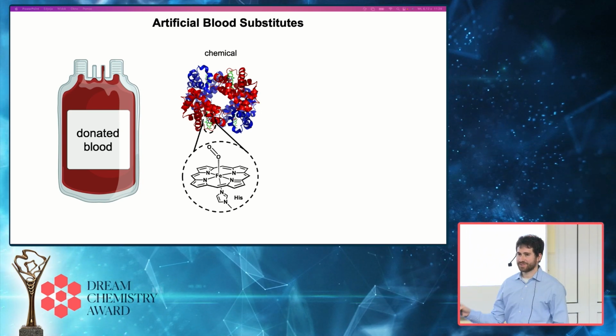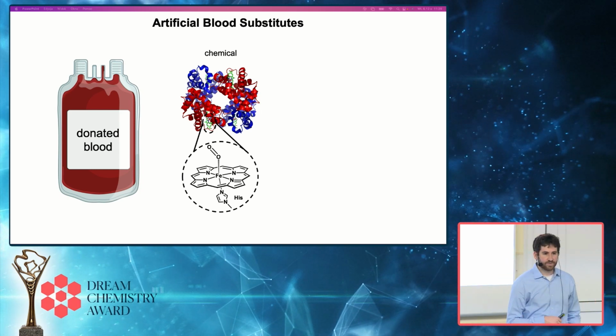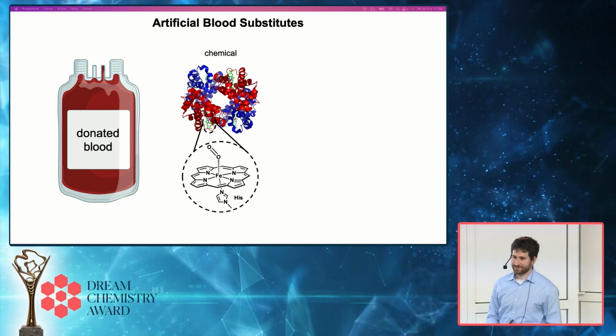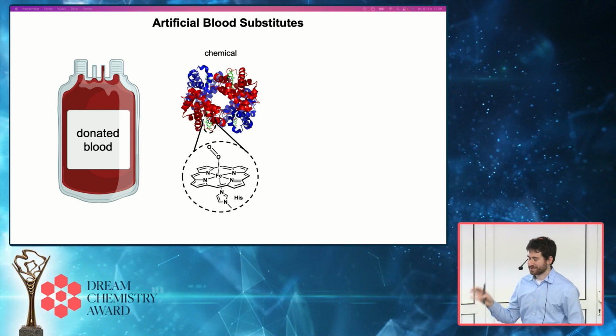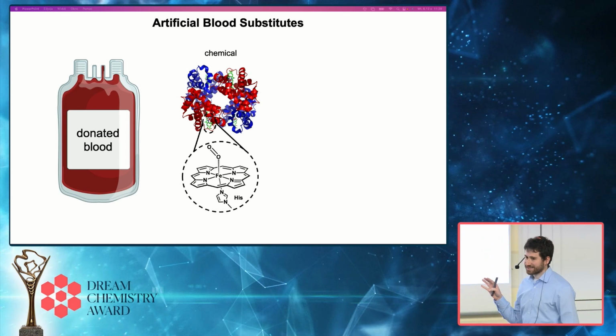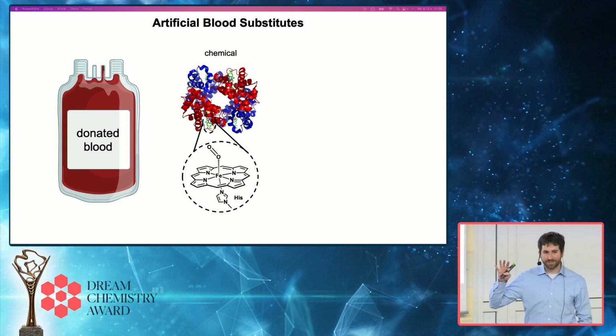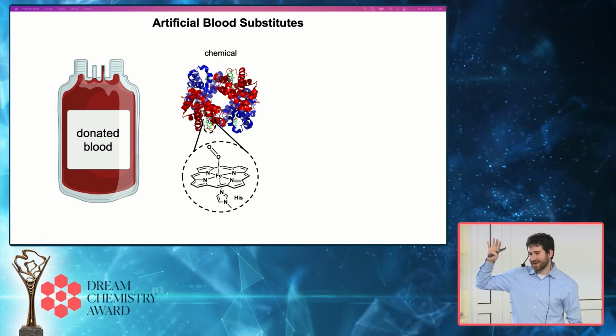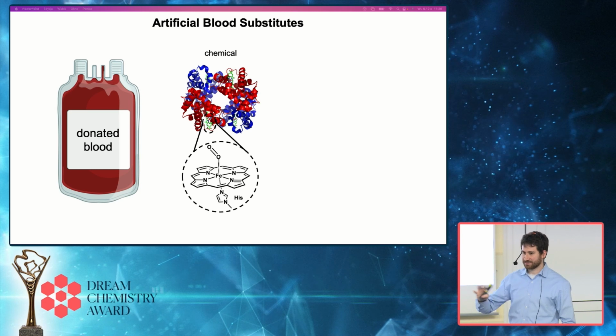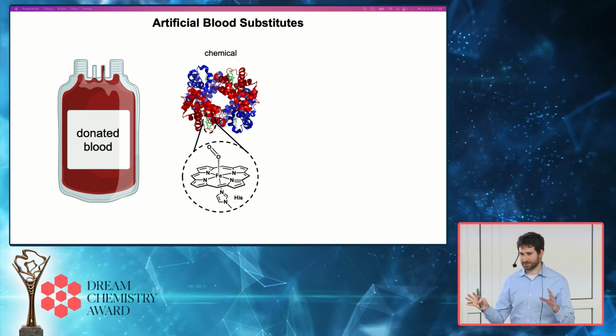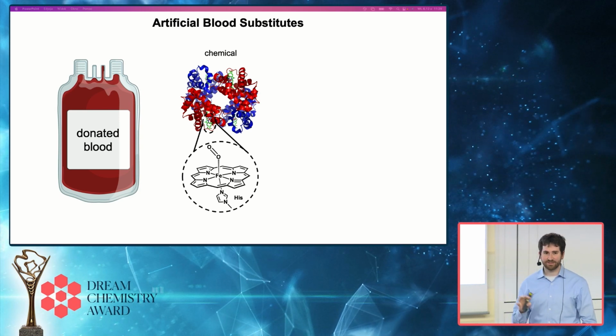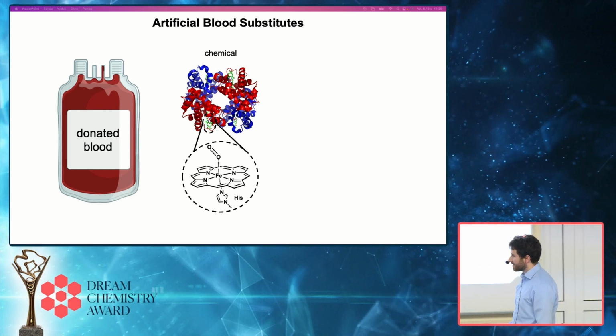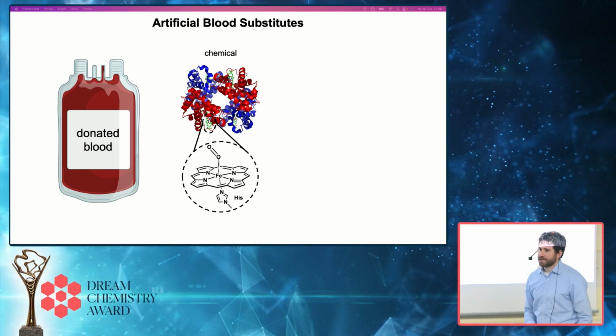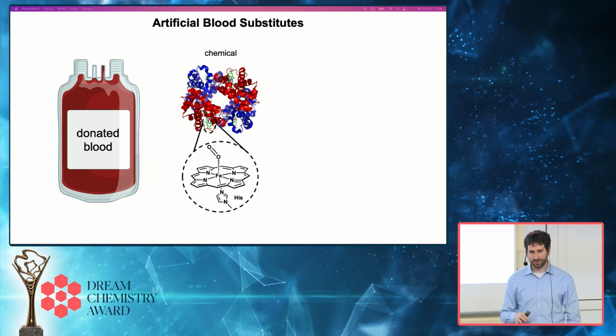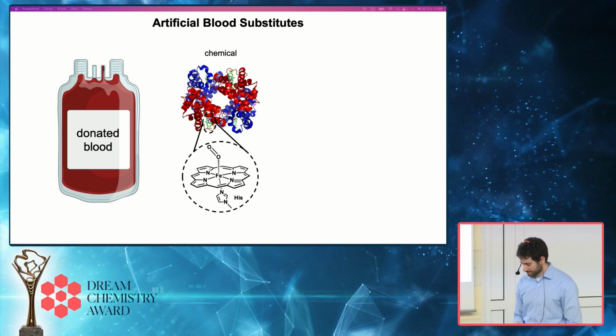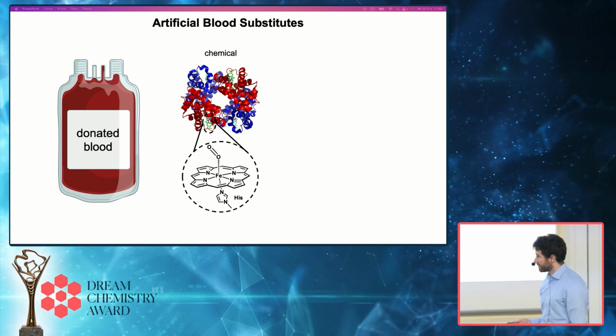It turns out hemoglobin itself, once you take it outside of a red blood cell, is actually very toxic and can induce a lot of kidney damage and can be really difficult to make cell-free hemoglobin that is both not that cytotoxic or has high biocompatibility, where also you get the binding between oxygen and these iron centers correct so that you can actually easily release it when it's needed. Red blood cells are a very finely tuned and regulated environment, and outside of that, it's difficult to get this to function properly. So there's never actually been in the US an FDA, Federal Drug Administration, approved hemoglobin-based product for transporting oxygen. And I believe that's true throughout the world as well.